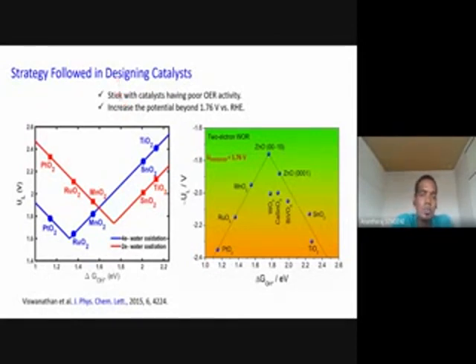So they proposed an alternate technology, which is nothing but direct synthesis, where they supply hydrogen and oxygen gas in a closed system for the two electron oxidation. Only these two principles are followed so far. You can either stick with a catalyst having very poor OER activity, or you can increase the potential beyond 1.76 volt. In this case, you have the possibility of accompanying four electron oxidation. But in the first case, you don't have such a chance, because this material is intrinsically poor or non-selective for OER. So realizing this, people have done so many works recently, and they found that zinc oxide is so far the best catalyst, which is actually starting hydrogen peroxide evolution at the reversible potential and also has very high selectivity.